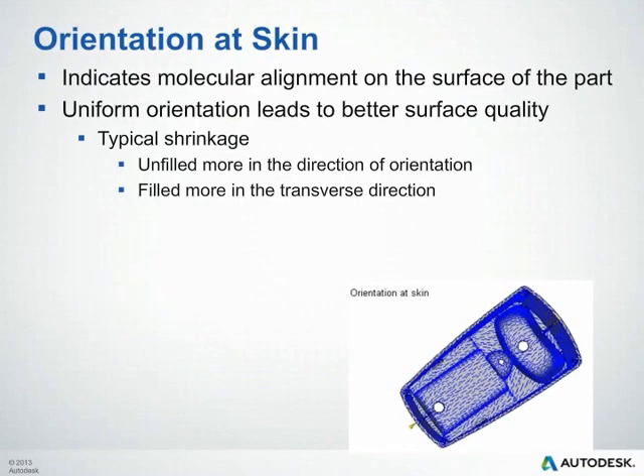You'll also receive an Orientation at Skin plot indicating the molecular alignment on the surface of the part. A uniform orientation leads to better surface quality. Keep in mind that unfilled materials will shrink more in the direction of orientation, whereas filled materials will shrink more transverse to the direction.